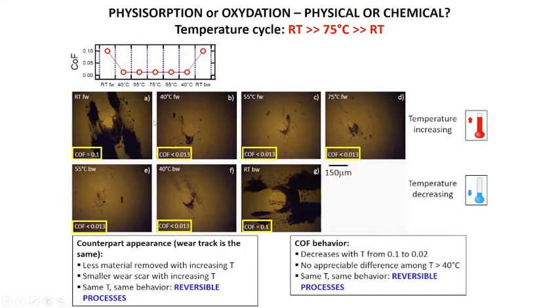And more or less the same results can be observed qualitatively if you look at the ball counterbody, because at room temperature you have a very large amount of debris on the counterbody here.